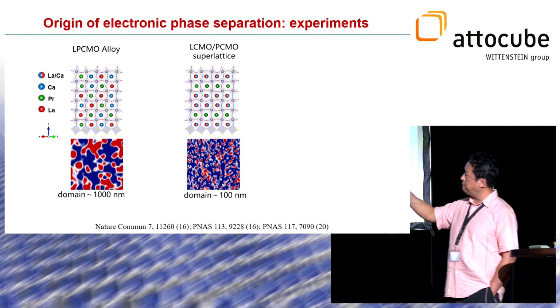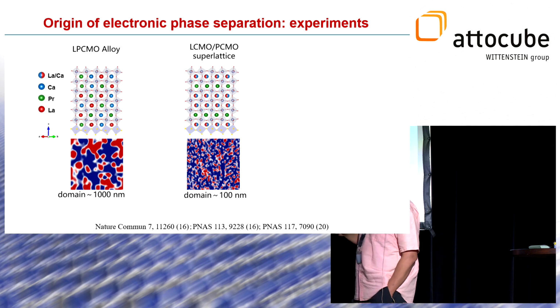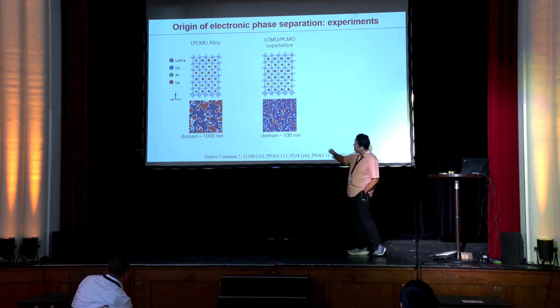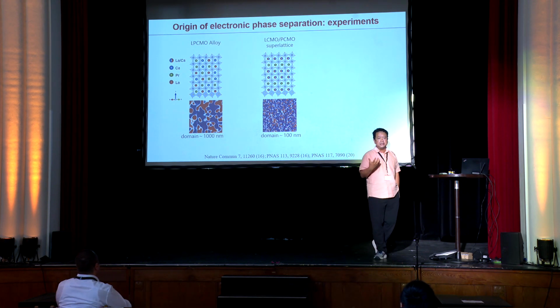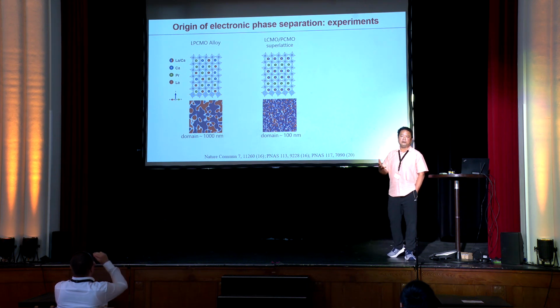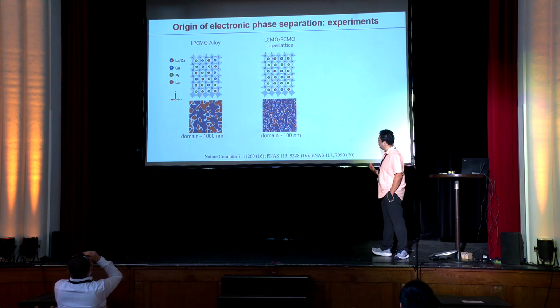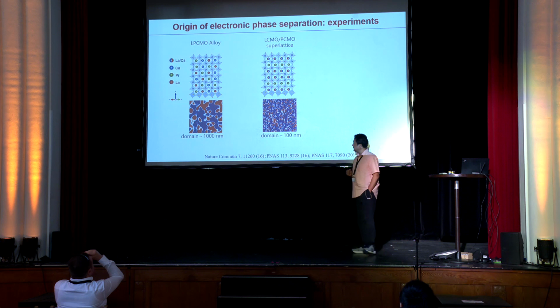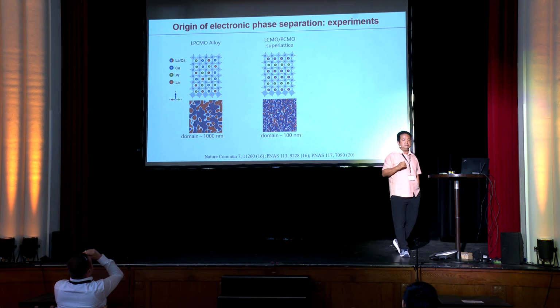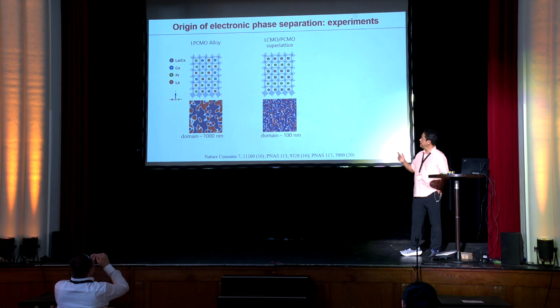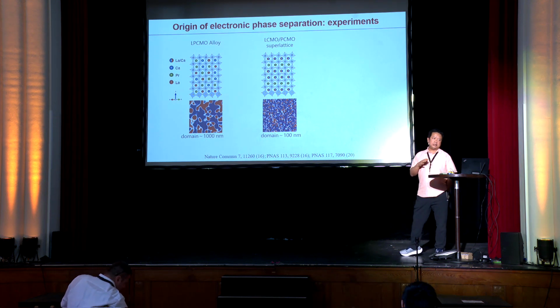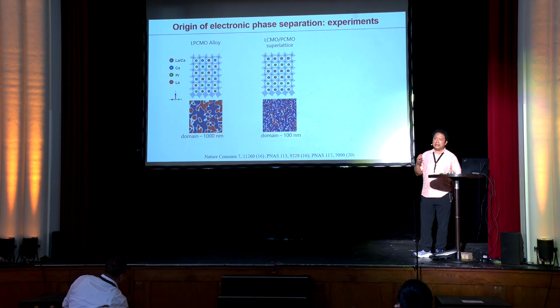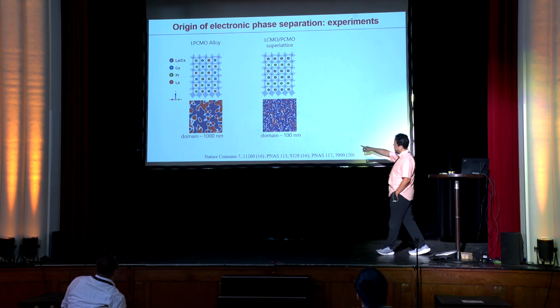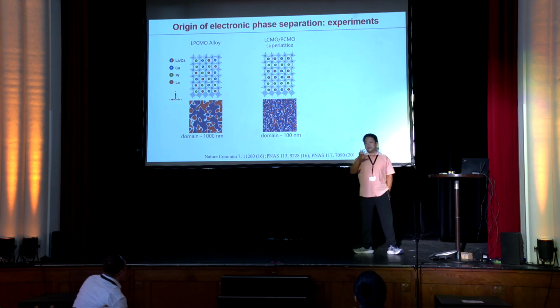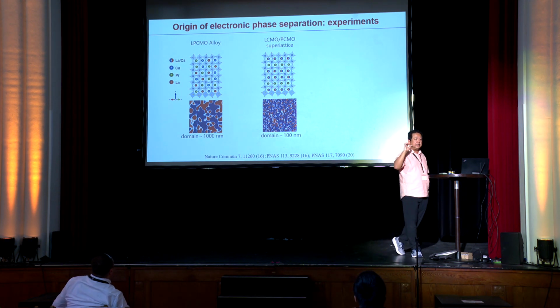So now you can compare these electronic phase separations. On the left-hand side is the conventional LPCMO thin film. The domain size is on the order of 1 micrometer scale. But now you can look at this praseodymium spatially ordered LPCMO. Now the domain size becomes an order of magnitude smaller. But in this material, the calcium dopants are still randomly distributed at the A site.